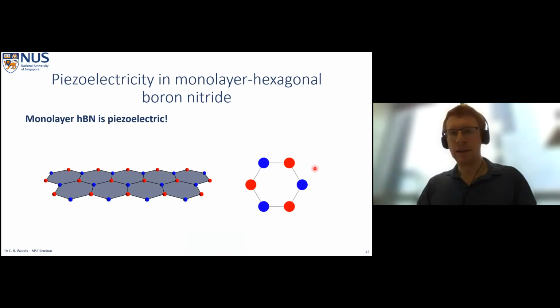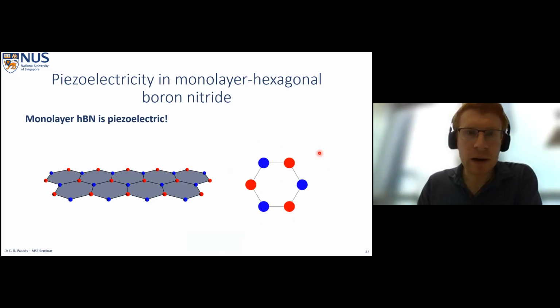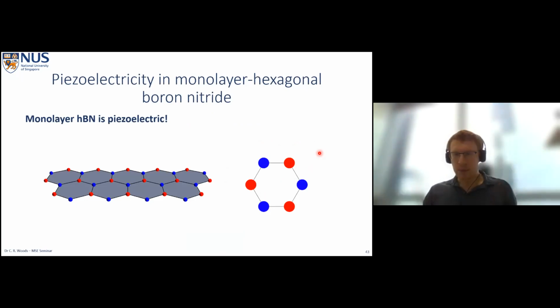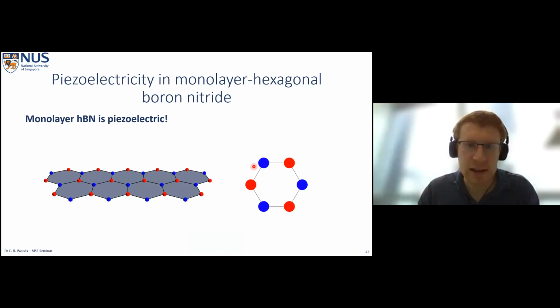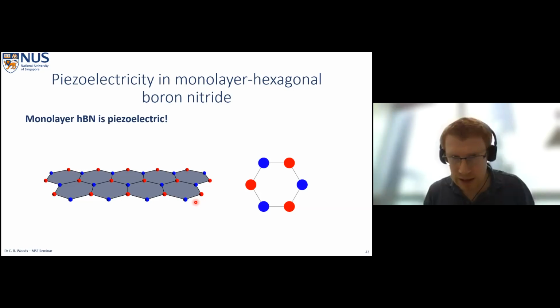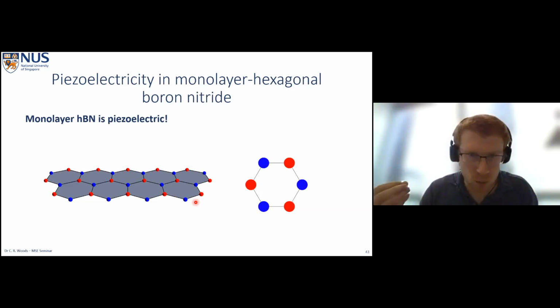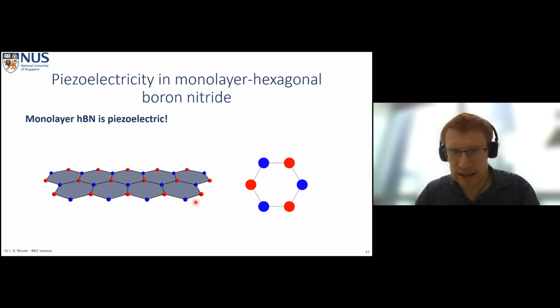Okay, so this is the first conclusion of this talk, which is that monolayer boron nitride is piezoelectric. And not only is it piezoelectric, but we can actually use this piezoelectricity to affect adjacent layers. So we don't just have to consider the edges of a uniform strain in our monolayer boron nitride to change the electric potential from one edge of the crystal to the other, but we can actually create a strain gradient within the crystal, and that will affect adjacent layers. So this is a really interesting mechanism, particularly for building up van der Waals heterostructures, where we're interested in layers affecting each other's properties.